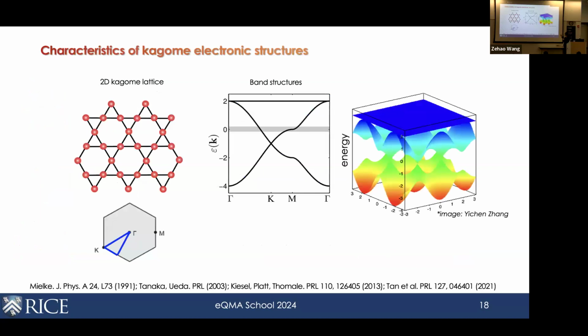I talked a little bit about the flat band here, but let me go back a little bit and show you what other interesting features there are in the electronic structure of a Kagome system. So these are band dispersions calculated by tight binding along the high symmetry directions in the Brillouin zone, so from gamma to K to M back to gamma. And this is a 3D view of this electronic structure over the two momentum axes. So this is the projection of the Brillouin zone here. Okay, so the first feature is the flat band. Of course, if you tune the chemical potential to be within the flat band, this gives a large density of states. And at least theoretically, this will lead to Stoner-type itinerant ferromagnetism, if you have, right, theoretically, at least this is what you would get.